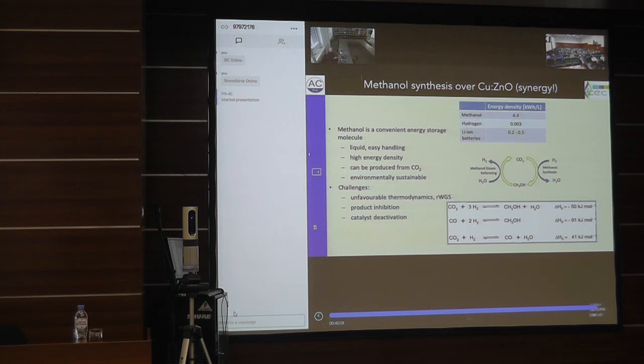And I want to make this very clear here: there is a lot of modern literature where people claim that they devise catalysts that have a better selectivity to methanol than they have for carbon monoxide. But then you will find when you read these papers that it works only in the limit of very low conversions, because then you are so far away from equilibrium that you are not bothered with the equilibrium formation of the reverse water-gas shift reaction. But when you want to run a catalyst at high productivity of methanol, then you inevitably have the problem of reverse water-gas shift. And how large that problem is, I will show in a few slides in a moment.